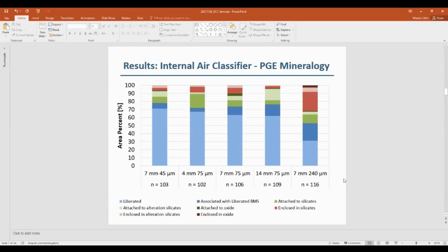We also did some mineralogy test work here, just looking at the PGEs, just the liberated, associated, attached and locked. If we look at the two outer bars and the central bar, this is for varying target P80 at a single grind size. And as we grind finer, yes, we do get better liberation. Just having a look at the first three columns in the center there, that's for different dam ring heights. So when we have an increase in dam ring height, from this data, it looks like there's a decrease in the amount of liberation.